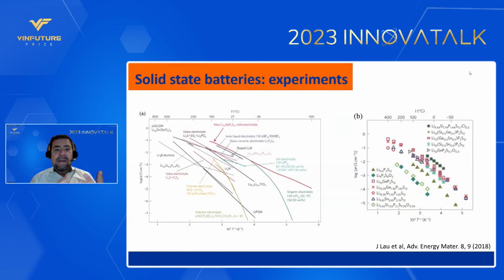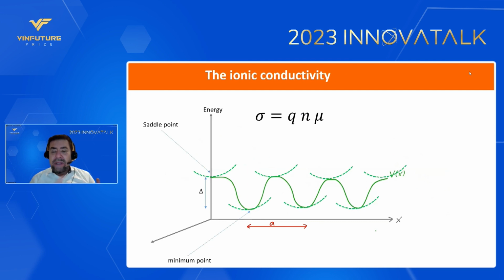So these are experimental data on several different types of solid electrolytes. On a semi-log scale, you see the log of the ionic conductivity plotted versus the inverse temperature. And what you see when you look at this data is that one thing is very clear: there is an exponential behavior going on. So the conductivity depends exponentially on the inverse temperature. Why is that? To understand this exponential behavior is actually relatively simple.